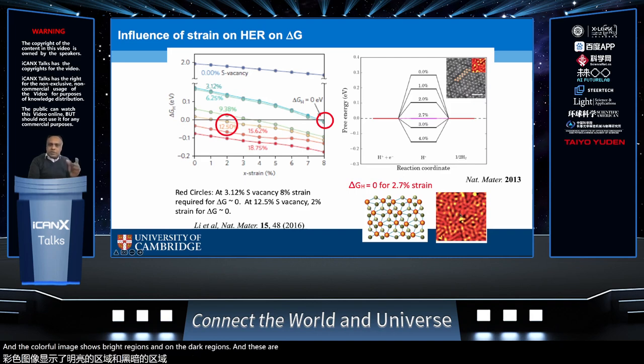And these are local regions of compressive and tensile strain on the order of 2 to 3%. What we found from the free energy calculation is that when you have MoS2 or tungsten disulfide in the 1T phase configuration, and that configuration is also accompanied by strain on the order of 2.7%, then the delta G at that strain value is zero, which is the ideal